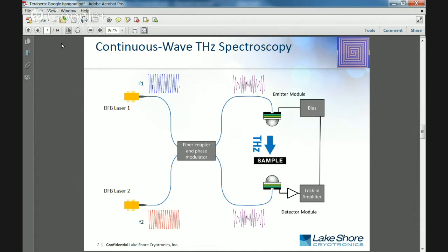It consists of two DFB lasers that are tuned to slightly different frequencies. When we add those two IR frequency lights together, we get an amplitude modulation of the IR light. Now we can use that amplitude modulation to both generate and detect the terahertz light. Because we're using these low-cost DFB lasers, the overall package is extraordinarily cost-effective compared with other terahertz solutions. And it's compatible with this approach of putting the sample as well as the emitters and detectors in the cryogenic environment. So we can fiber couple to our emitters and detectors, again eliminating the optical alignment challenges that would come with conventional approaches to doing cryogenic or high magnetic field spectroscopy.